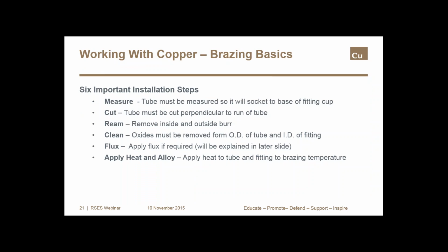Here are six installation steps that will ensure an effective brazed joint. Measure, cut, ream, clean, flux, and heat. All of these steps are important. The tube must fit all the way into the base of the fitting cup, so measuring the tube is critical. The tube must be cut so it's perpendicular to the tube run, and then any burrs must be removed.